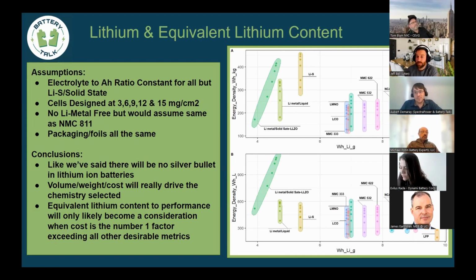The 0.5 is actually for LCO, lithium cobalt oxide, not for LFP. With LFP, you can pull an entire lithium out of LFP. You cannot pull an entire lithium out of lithium cobalt oxide because the structure will collapse. Yep. Amber, you are rapidly pointing out problems I don't want to explain. I built like 50 batteries.